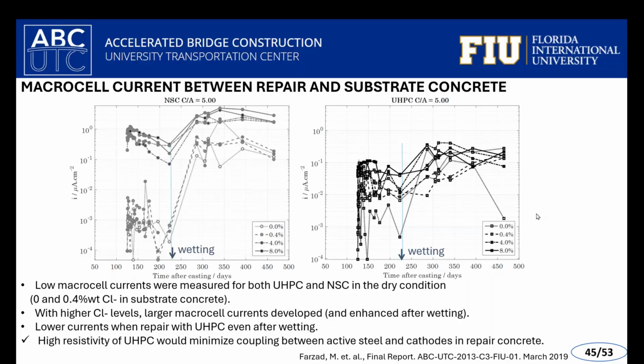So this became interesting to us, as UHPC is of interest in retrofit for some of the more adverse damage for marine systems or a chloride contaminated system. Even carbonation can be partly alluded to as well. Of course, the caveat is it depends on the size of the repair and the placement of different rebar and oxygen availability. But some promising results show a beneficial effect with the UHPC.